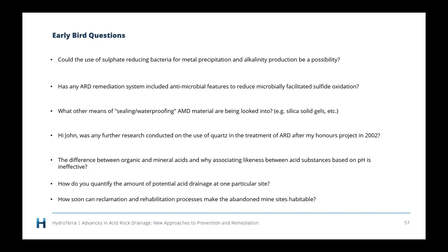It's interesting to know. Next question. What other means of sealing / waterproofing acid mine drainage material are being looked into, e.g. silica, solid gels, etc.? So there was a company that marketed a product which would encapsulate acid producing material like waste rock with a silica coating, with the idea of permanently locking it away. What they used was a mixture of fine-grained amorphous silica and calcium hydroxide, because the calcium hydroxide, when you added water, made the solution very alkaline. That put the silica into solution. You added that to the waste rock, and that brought the pH down and automatically precipitated the silica.